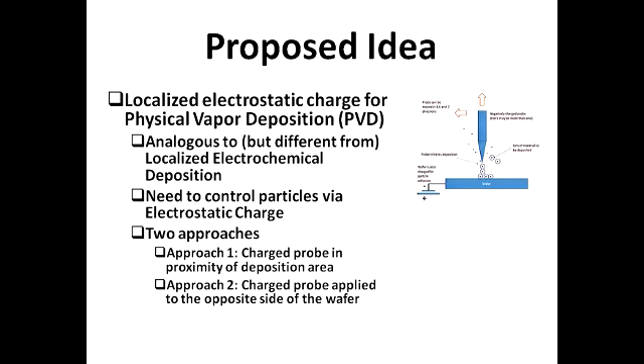This is another method that we propose here, and it is very analogous to the electrochemical one: localized electrostatic charge for physical vapor deposition. In this method, we need only to control the particles by electrostatic charge, and we do not need any chemical reaction or any chemical. We only work with a probe and our wafer or our substrate. There are two ways to do this method. One of them is a charged probe in proximity of the deposition area. Another one is a charged probe applied to the opposite side of the wafer.